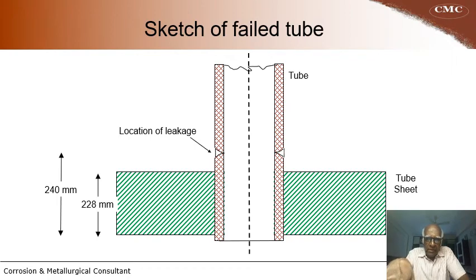This is a sketch of the failed tube. You can see the tube sheet, which is a plate of about 228 mm thickness, and the tubes are drilled and expanded into the tube sheet, and you can see the position of the leakage is about 240 mm from the tube sheet outside surface. From the inside surface, around 12 mm (240 minus 228) layer of water has been remaining, and that layer has led to this corrosion. And this layer in a boiler water is alkaline. That is why it is called caustic gouging. And you can see in the next slide the positions of the various nozzles.